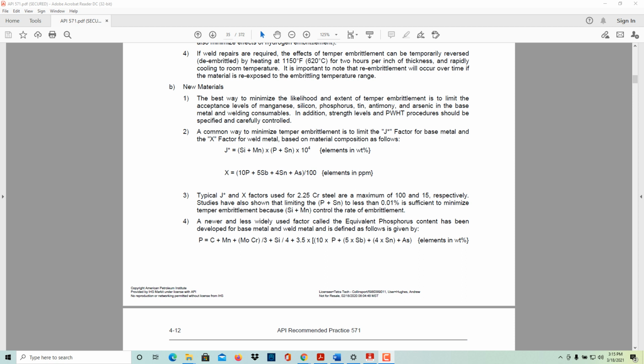A newer and less widely used factor called the equivalent phosphorus content has been developed for base metals and weld metals and is defined as follows: phosphorus equivalent equals carbon plus manganese plus the product of moly and chrome divided by 3, plus silicon divided by 4, plus 3.5 times (10 times phosphorus plus 5 times Sb plus 4 times Sn plus As), elements in weight.